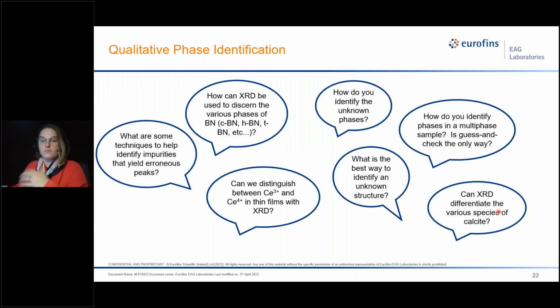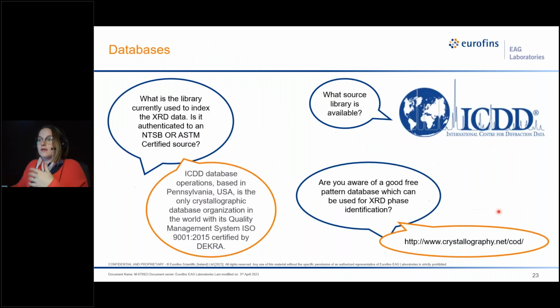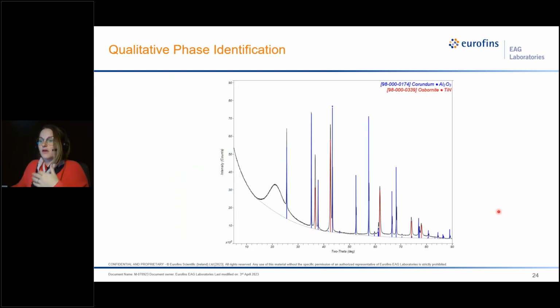So the first, most simple kind of qualitative information you can get is what's in my sample. And to do that, we need to have databases. For the database that we use, the ICDD, there are about 500,000 entries. So again, I was mentioning those diffraction peaks. Now, in this example, we've got two types of phases: a corundum and a titanium nitride phase.